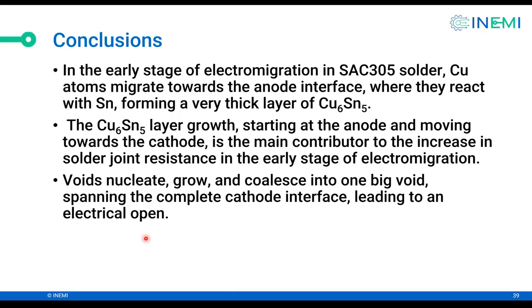But then later on, at the later stage, void nucleation occurs, they grow, they coalesce into one big void that spreads across the span of the solder, and completely covers the interface, and that leads to an electrical open.